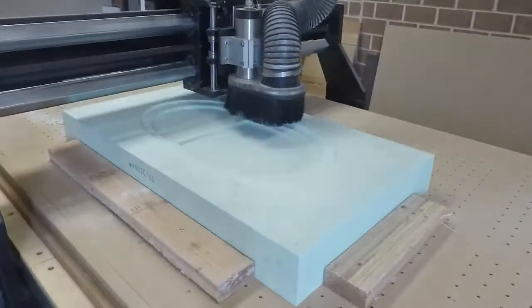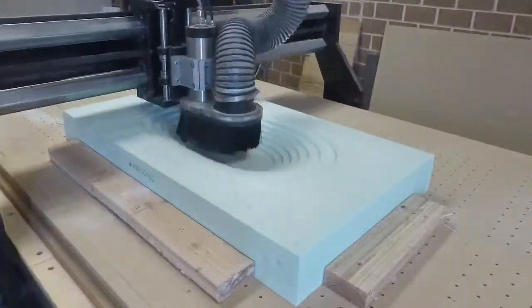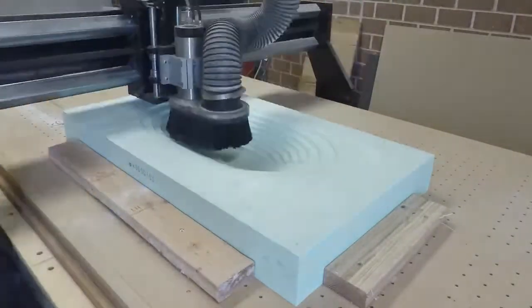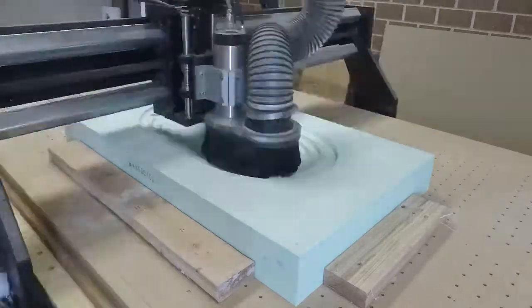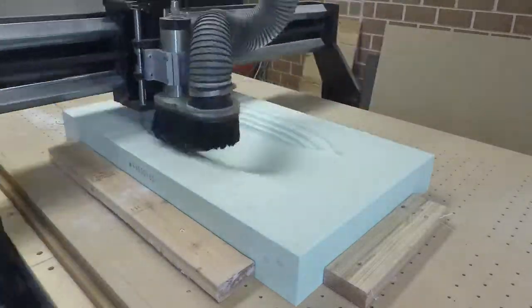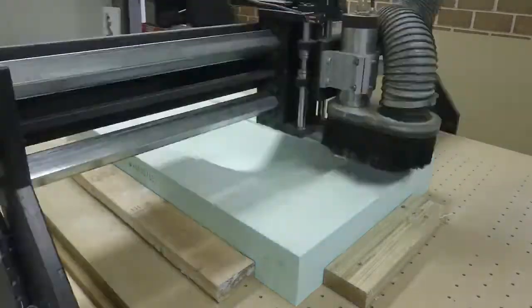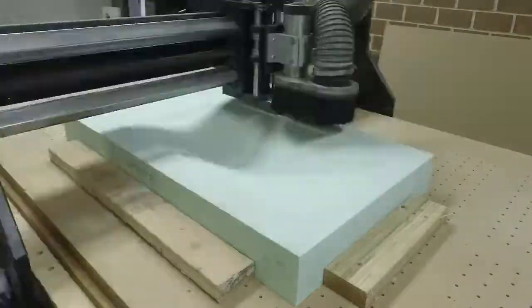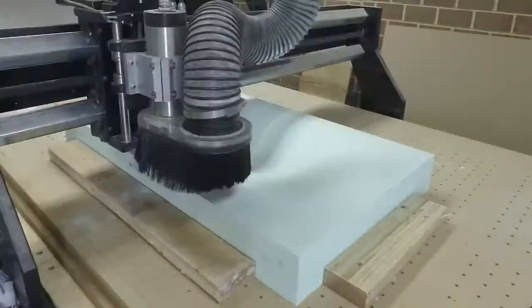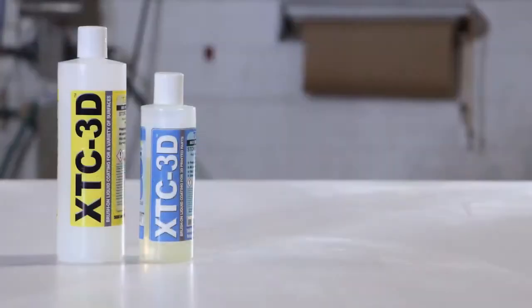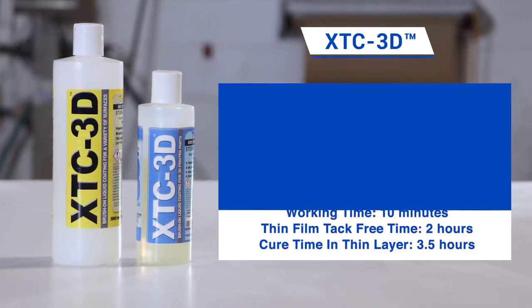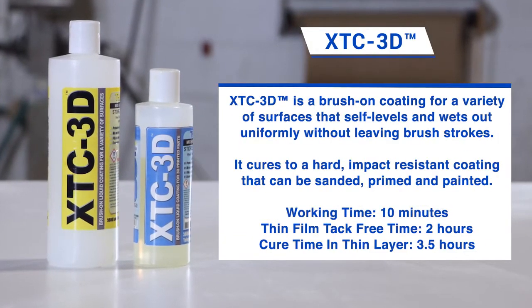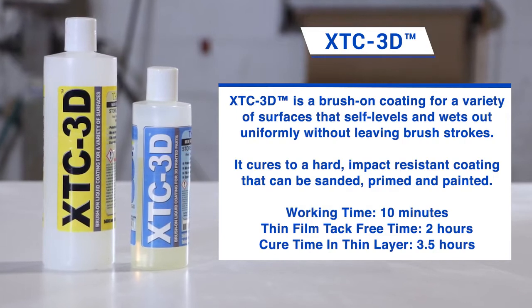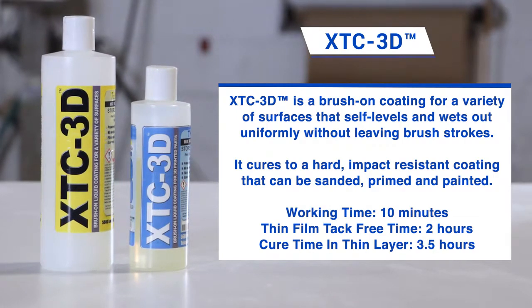The profile was cut using 15-pound tooling board, and this became the model. Texture and tooling marks from the CNC machine need to be filled through an application of an epoxy coating. This rigid coating will also protect the model's surface and eliminate porosity prior to mold making. I chose XTC-3D for its short pot life, 10 minutes, and tack-free in approximately 2 hours.